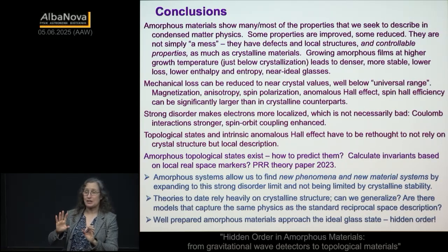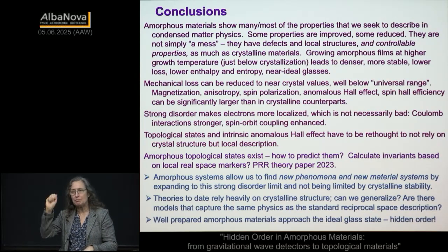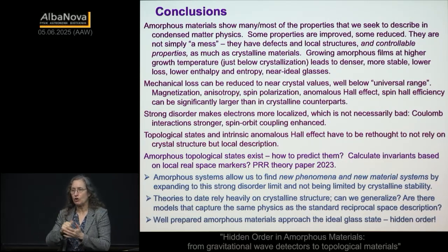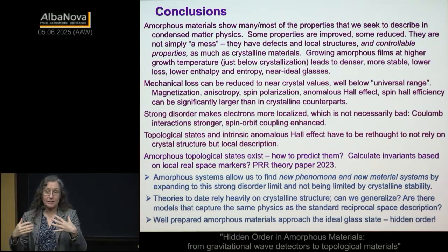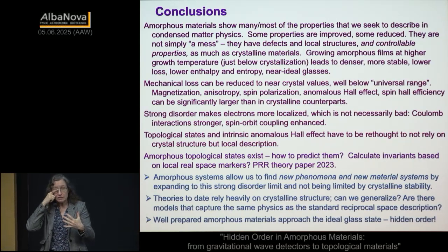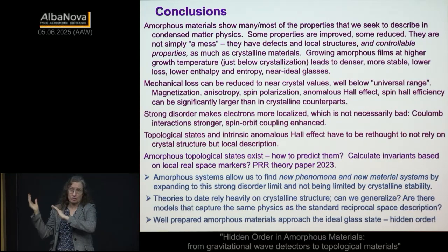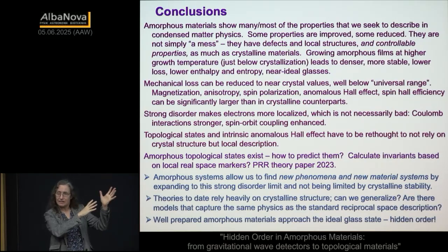Sputtering does not do that. Sputtering, because you're doing this high energy peening, as it's often called, it's high energy, so it's literally like a ball peen hammer. So you end up with a very different structural appearance. We've grown amorphous silicon by sputtering also, by the way, and then it doesn't have those columns.